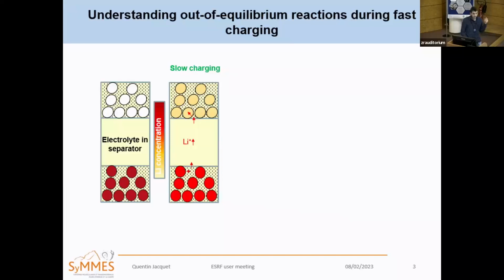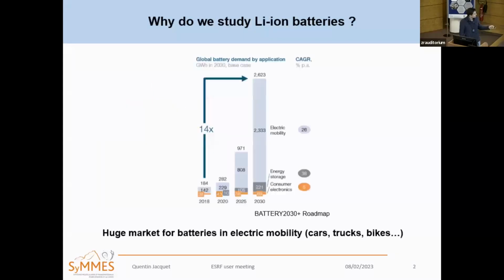And for electric car, one of the main issues is to be able to fast charge this battery. And fast charging leads to out of equilibrium reactions, which I'm going to describe here. So basically, this is a schematic of a lithium-ion battery with the color being proportional to the lithium concentration. So you have your lithium in your electrode at the beginning of your charge, and as you're charging, lithium basically travels from one electrode to the other one. But if you fast charge it,